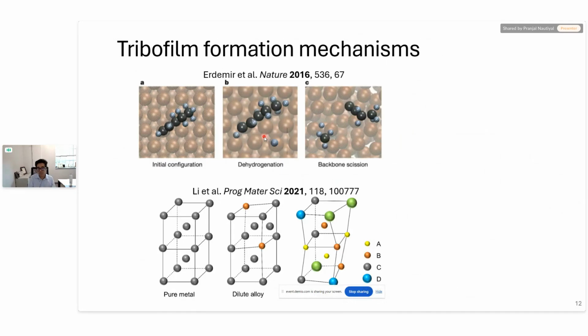And that lattice distortion is believed to promote catalytic activity because that causes the potential energy of the alloy to be high, and that reduces the effective energy barrier for chemical reactions. So we think that this is a very important mechanism that provides enhanced catalytic activity in these high entropy alloy catalysts. And so we can exploit their catalytic activity to design mechanical systems, mechanical components, coatings, that can provide excellent wear resistance by generating lubricious tribofilms from ambient air.